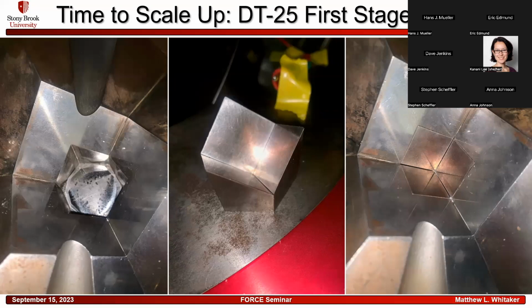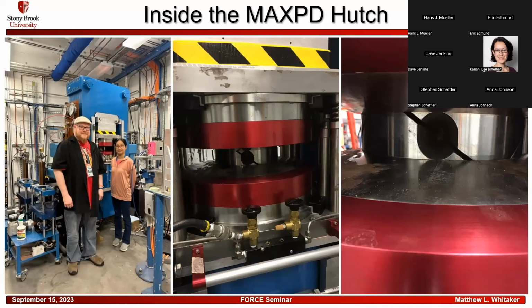And this is a picture of the inside of the DT25, where we have the piston exposed on the left. We have these three little tripartite wedge pieces that we put in the hole space there in order to form a surface that's very similar to a regular 111 geometry Kawai press. And we can then again actuate the top and bottom anvils separately. Inside the MAX PD hutch, we have the 1,100 ton press that's shown behind me here. As you go from the left to the right, you get closer and closer to your sample. You can see the hole cut in the middle there; that's where the X-ray beam enters. And there is a symmetrical hole cut on the backside, which is where the X-ray beam exits the sample.